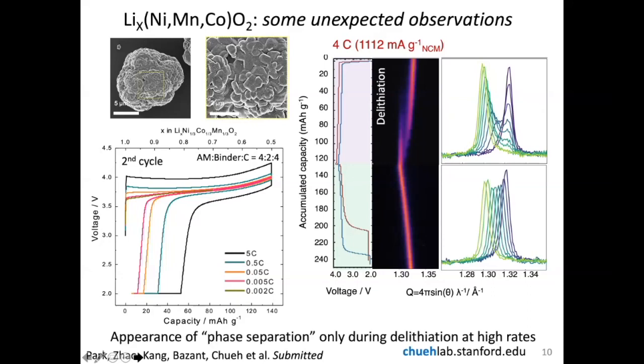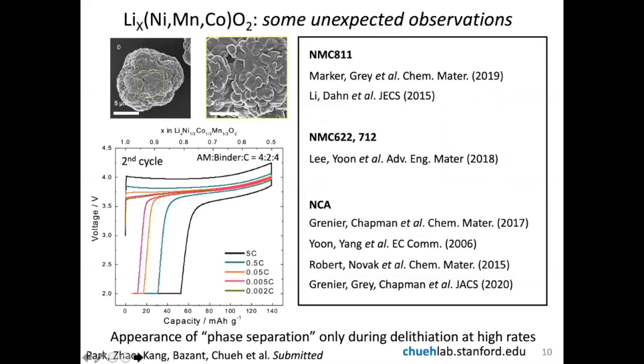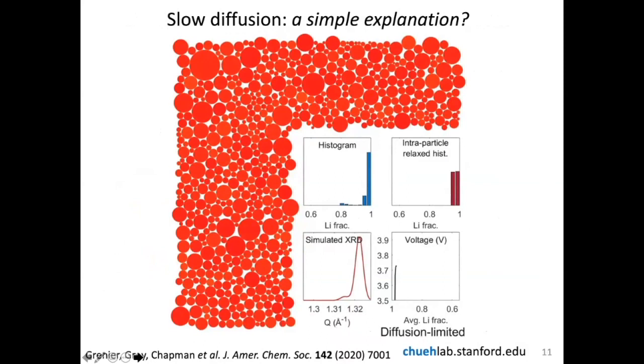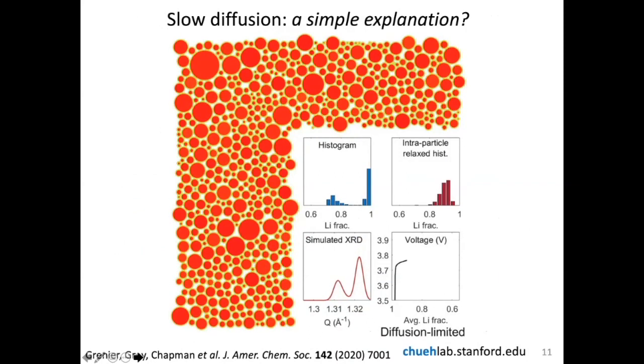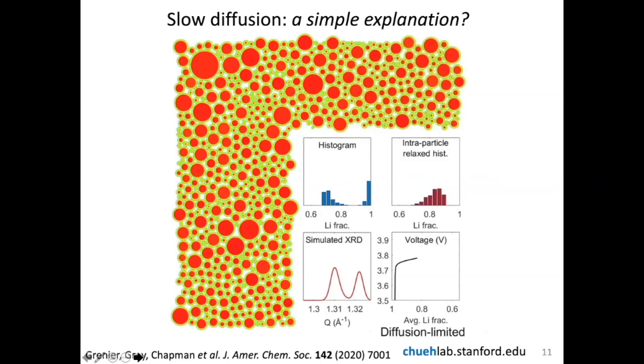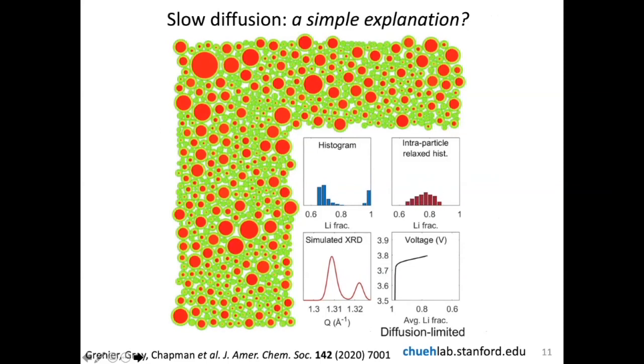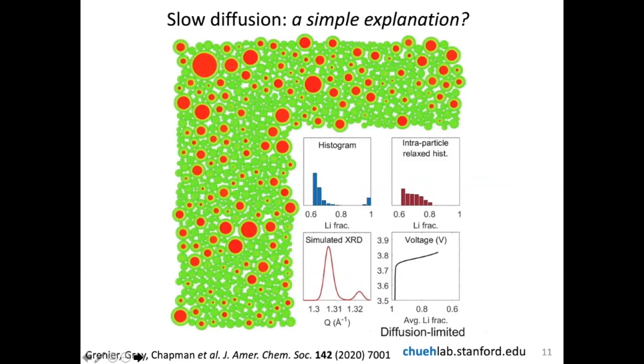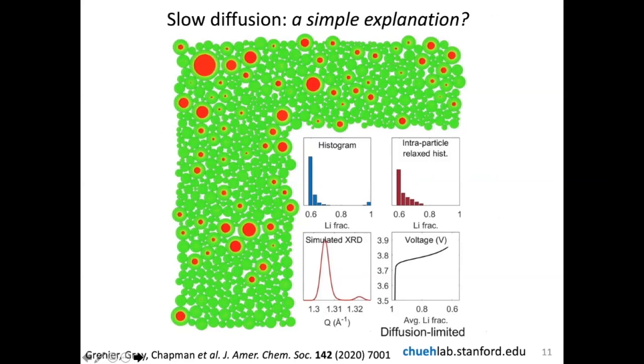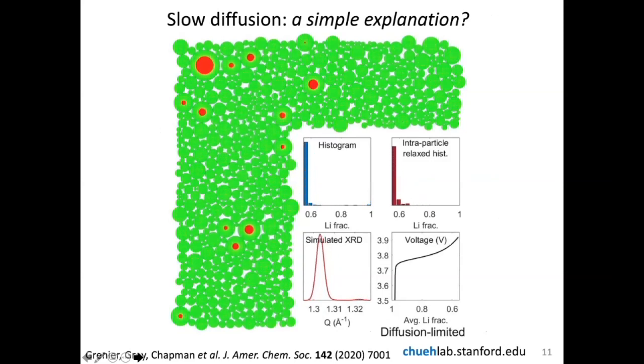This has actually been reported quite a number of times in all sorts of cathodes: NMC811, 622, NCA. The first observations were made about a decade and a half ago and were also recently reported by Karena Chapman and Clare Grey. And the simple explanation for this is diffusion. So here I'm showing you just a schematic of what happens when diffusion is slow within the primary or the secondary agglomerate within the cathodes. You will begin to develop a moving front in the material. And when you do X-ray diffraction, I'm showing the diffraction on the lower left plot here, you can see the emergence of two peaks as you delithiate, as you charge the material.